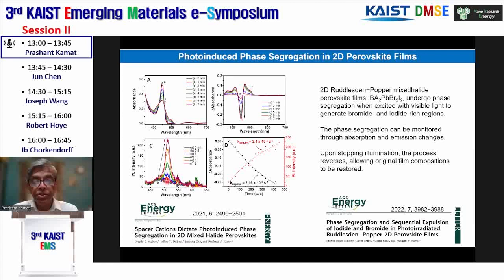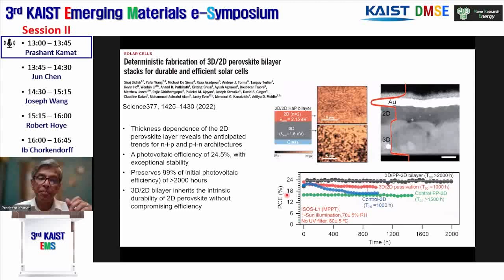This is the very weak emission from the mixed halide around 475 nanometers or so. And now it shifts to the iodide-rich region of this emission. We can follow this emission region or the decrease in absorbance, and we get very similar rate constants. So these 2D halide perovskites also behave the same as 3D.